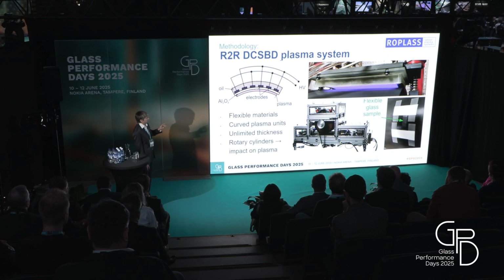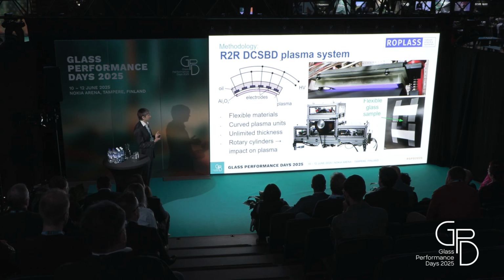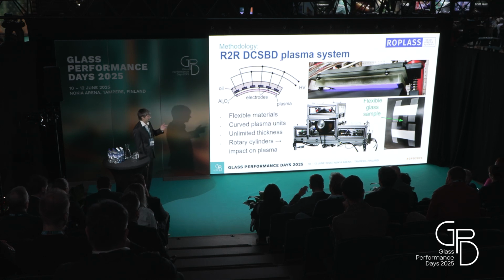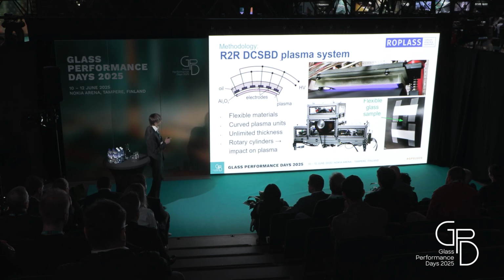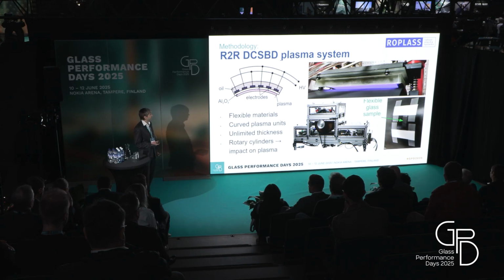And we place the samples on the roll. That's why I show you this picture, because we see that this covering of the sample has an effect: the plasma is in a very thin layer, so it's hindered from burning over these paper holders. And the reactor which I used is also suitable for use with another gas if you want to do some other application.